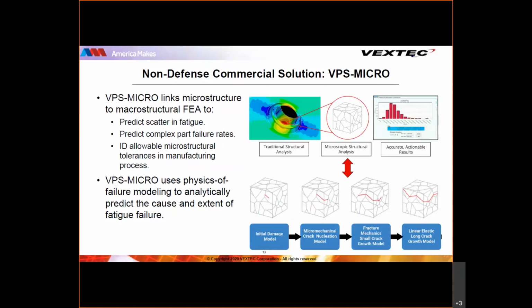And not only can this be used to predict the risk of failure of a structural feature, but it can also be used, in the design sense, to know what microstructure is allowable at each location of a part. And this is especially important in AM metal products where the microstructure can vary throughout the part depending upon where that location is on the build plate, how thick that particular location is, and during the processing, the heat transfer that takes place in the creation of that microstructure.